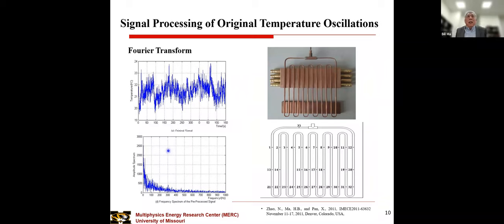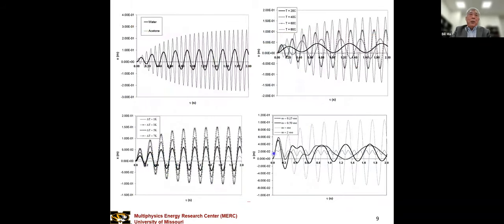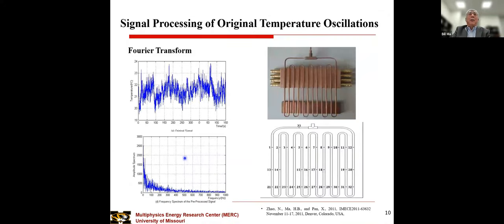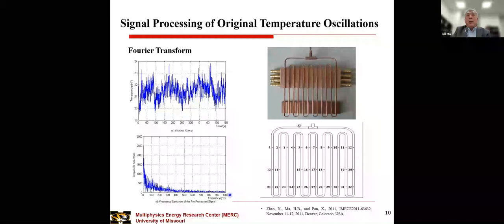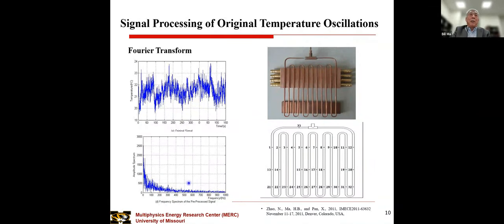So you can see that the measurement is from the temperature oscillating motion for a given heat pipe. As we know here, when the power goes up, the frequency is almost the same, and that's not right. Therefore, we need to analyze and find out how many frequencies there are for a given heat pipe. That's a measured temperature variation. Using a Fourier transform, we found frequencies from 0 up to 1,000, so many frequencies.